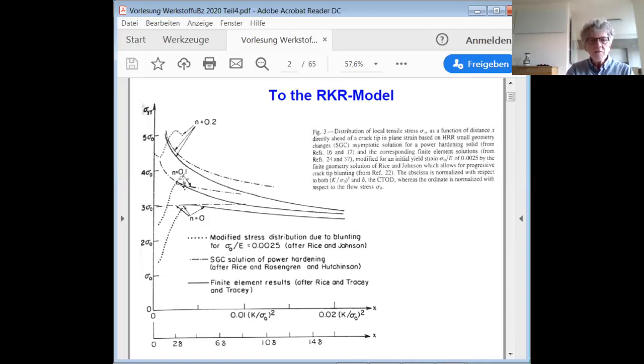What you also see in the dotted lines here is that in reality, due to the blunting of the crack tip, the stresses decrease very low very near to the crack tip. Okay.